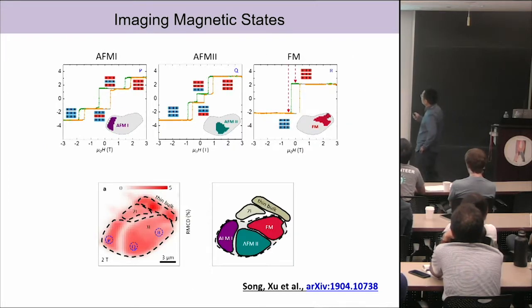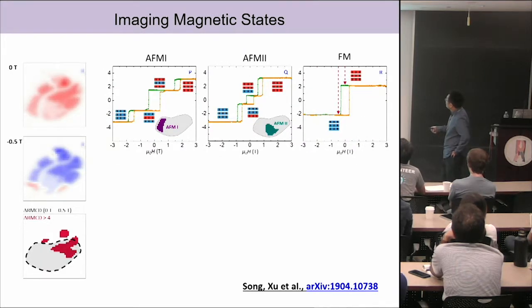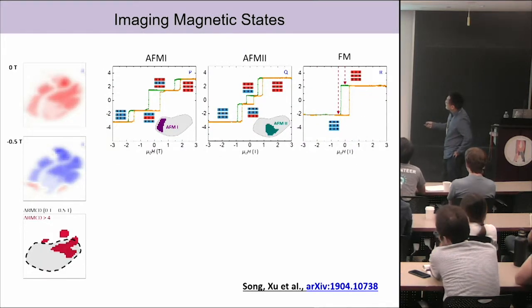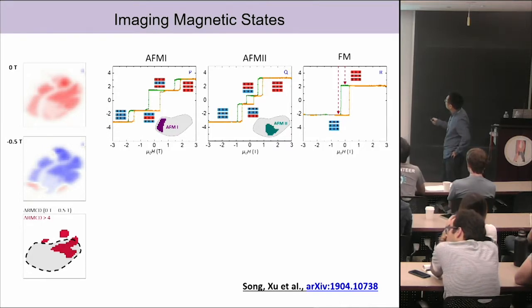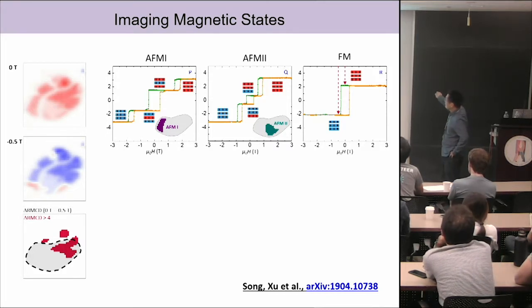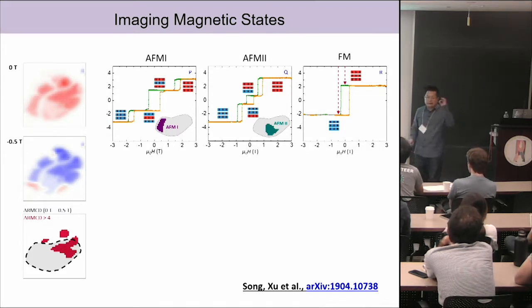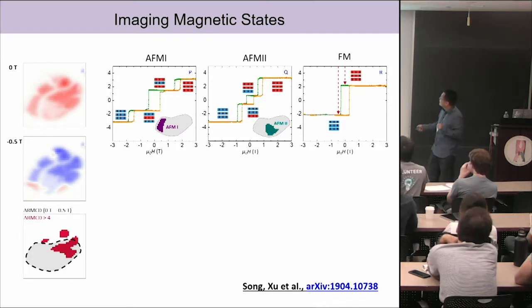Last, let's try to map out the ferromagnetic states. It's a little more tricky for the ferromagnetic states. Let me go back a little bit. We take a map at 0 Tesla and minus 0.5 Tesla. So for these two fields, the antiferromagnetic phase 1 doesn't change, but the ferromagnetic phase also has spin flip transitions. But there's a difference. You can see the signal change for the ferromagnetic phase is much larger than the signal change found in antiferromagnetic state 2. So you can see the large drop here, larger than 4%. So what I do is take a difference of these two maps, but set the signal threshold larger than 4%. Then we can isolate this area for the ferromagnetic states.